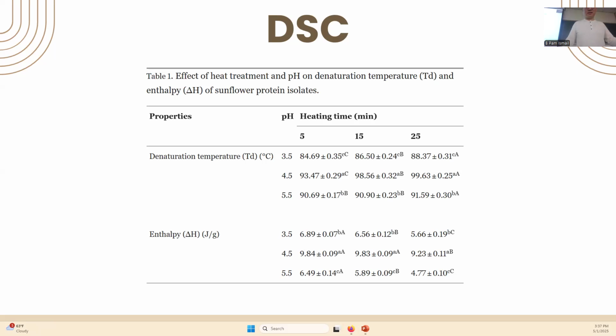In the paper, they just said at pH 4.5, the isoelectric point, the enthalpy is the highest. This is opposite to theory as far as I'm concerned, because the protein is most susceptible to denaturation at the isoelectric point, because you lose charge on the surface. So they are susceptible to unfolding. It's a very strange result, I would say. It's not you, it's the paper.